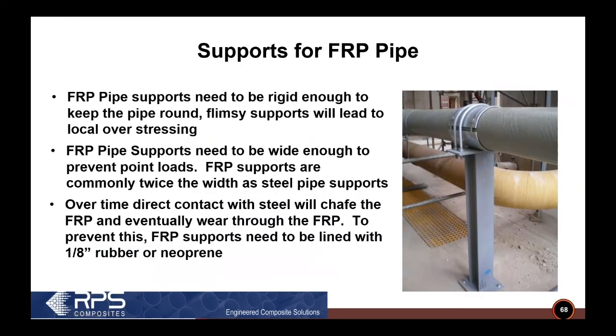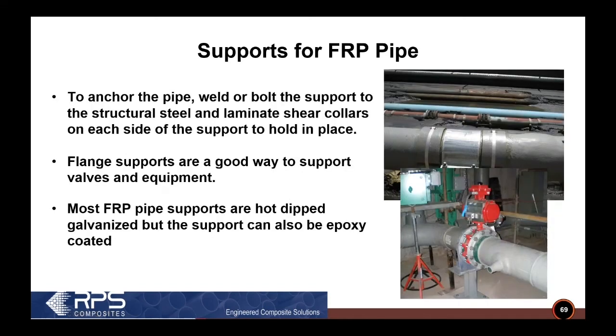The pipe supports need to keep the pipe rigid. It can't be flimsy. That would allow local overstressing of the piping. The supports need to be wide enough to prevent point loads. Commonly, they're twice the width of a steel pipe support. And over time, you can't have steel directly contacting FRP. It'll chafe the FRP and eventually wear through it. And to prevent this, we normally line the FRP pipe supports with an eighth of an inch of rubber.